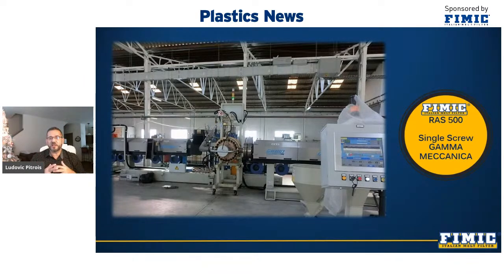Regardless of the extruder brand our customer chooses, we adapt our filters to the extrusion line they selected. For example, this image shows a Gamma Meccanica extruder in tandem or cascade configuration for degassing highly printed, wet, and contaminated film. They process unwashed low-density PE, commercial origin, at a capacity of 1,000 kilograms, equivalent to 2,200 pounds per hour, using a 500 millimeter diameter RAS-type filter. We start with cascade lines because normally many extruder brands for post-consumer prefer to use two-stage extruders. But obviously, most brands that do cascade also manufacture standard lines.